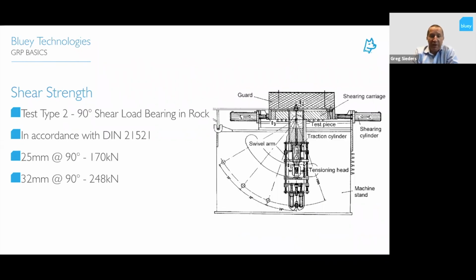Two other shear tests that we've carried out, which is under load, is the 90-degree shear testing to the German standard, the DIN standard there. We've tested both 25 mil bars and 32 mil bars for the application, and you can see there the capacity of both bars is equivalent to a steel bar. Then the other test that we carried out was a 50-degree shear. This is more for your soil nailing application. When your bars are activating, you're putting a bit of tension onto your fibres, which increases the shear capacity. Hence you can see the greater shear capacity in your 25 and 32 under this 50-degree shear testing. We'll cover a lot more of this in the coming weeks when we go into a bit more depth about the shear testing and test standards.